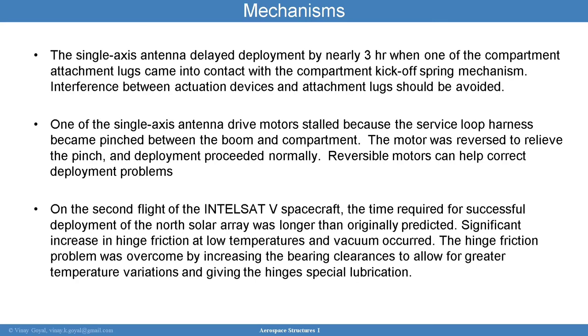And on the second flight of the Intelsat 5 spacecraft, the time required for successful deployment of the North Solar Array was longer than originally predicted. A significant increase in hinge friction at low temperatures and vacuum occurred. The hinge friction problem was overcome by increasing the bearing clearances to allow for greater temperature variations and giving the hinge special lubrication.